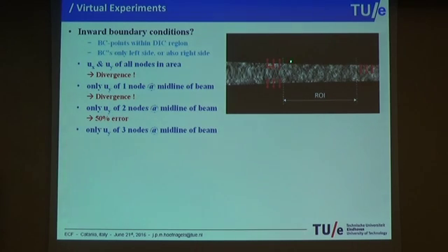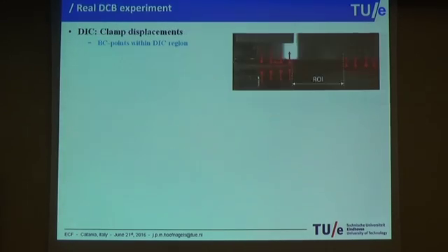If we have 3 points, we can actually describe the curvature locally on these points. Now we're getting closer, 10% error. But now we realize that the curvature is linearly changing. So if you would have 4 points, we would impose a bit that this curvature changes linearly, and this would work inwards in this region where we want to correlate. Now we're getting very close. Less than 1% error.